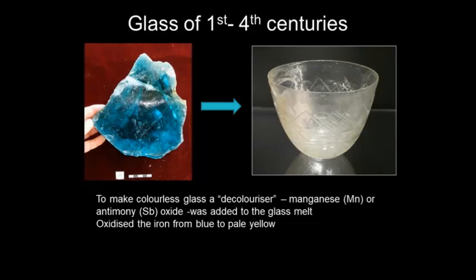When glass comes out of the tank furnaces, these chunks are usually green or blue in color, making bluish tinted vessels. But they wanted colorless glass, and they learned that if you added a small amount of antimony or manganese when you made it, you ended up with a colorless glass which was much more attractive, resembled rock crystal as Pliny says, and took decorations such as carving much better. So they learned this technique called decolorization — adding a decolorizer, manganese or antimony oxide, to the glass.